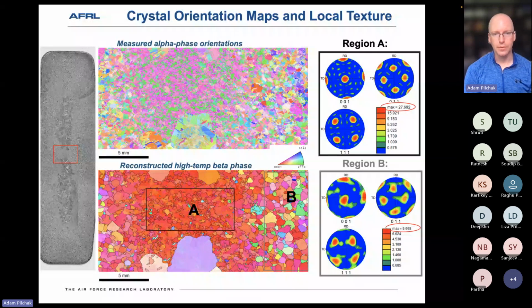During my dissertation work, I developed a code to do that inverse calculation, so taking the measured alpha phase orientations and knowing the orientation relationship between the alpha and the beta phase, it's possible to recalculate what the high temp beta phase must have looked like to produce the microstructure that we ultimately observed at room temperature. So that's what we've done on the bottom here.